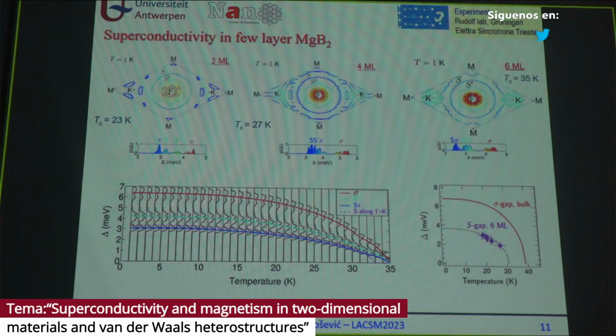From adding 1 layer at a time or 2 layers at a time. And we did the measurement in synchrotron. The samples were grown in Petra Rudolph's lab in Groningen, and in Elettra in Trieste, they measured the surface gap of a 6 monolayer sample, and it ideally matched the prediction of the theory of this purple dashed line here. Quite impressive, actually, what can be done.